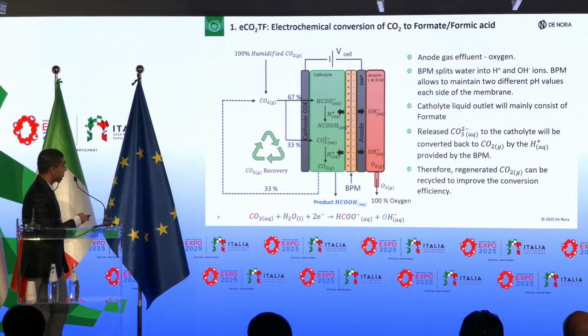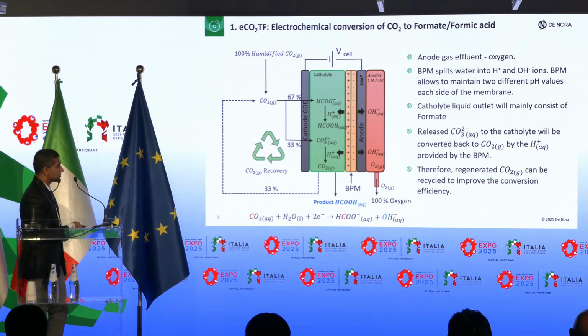Then we have this finite gap, which contains the catholyte, typically a potassium bicarbonate solution. And then we have a De Nora gas diffusion electrode with a catalyst, where we feed carbon dioxide, and this catalyst converts the CO2 to formate. And this formate can combine with protons, resulting in formic acid.